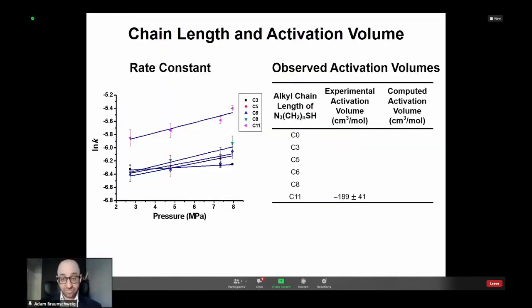So what we did was we repeated these experiments with different alkyl chain lengths. And then in collaboration with the Houk group at UCLA, they computed activation volumes based on the single conversion of an anti-conformation to an eclipsed conformation, which would cause the chains to bend. So on the left are our values, and on the right were the computed values.